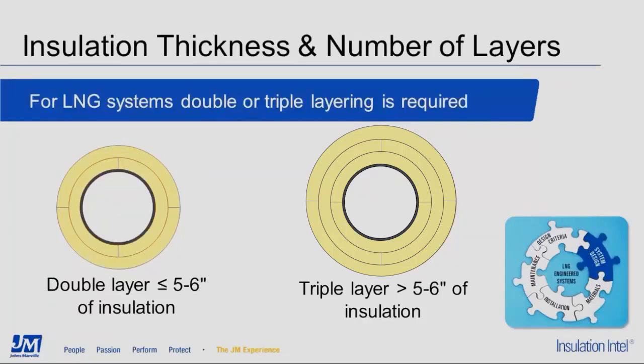The number of layers used will be either 2 or 3 for the 2 most commonly used LNG insulation materials, PIR, that's polyisocyanurate, and cellular glass. Whether it is 2 or 3 layers depends on the total insulation thickness required. For a total thickness less than around 5 to 6 inches, a double layer system would be used. At a total thickness above this, a triple layer insulation system would typically be used. And again, that's for cellular glass and PIR.